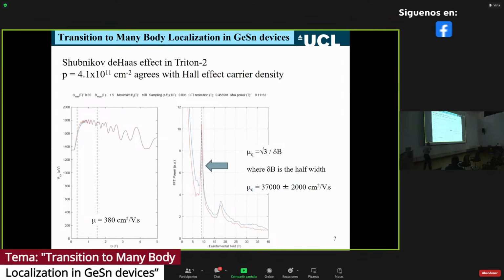Interestingly enough, we've still got this high level of disorder. And the first measurements that we did, we cooled it down in the cryostat. I think this is 1.5 Kelvin. We cooled the device down in the cryostat, applied a magnetic field. So this is actually almost the raw data. This is just the voltage drop along the device, so proportional to the resistivity as a function of magnetic field.